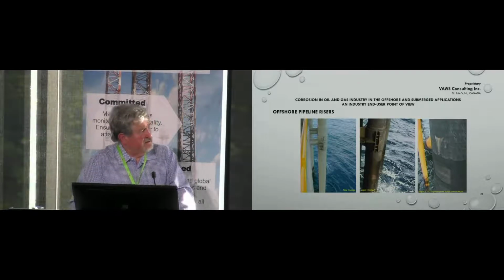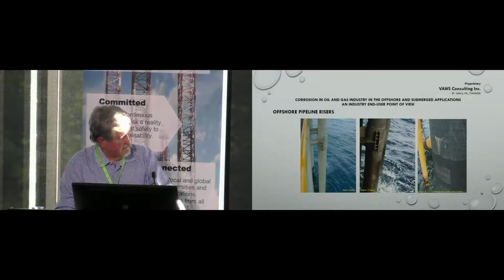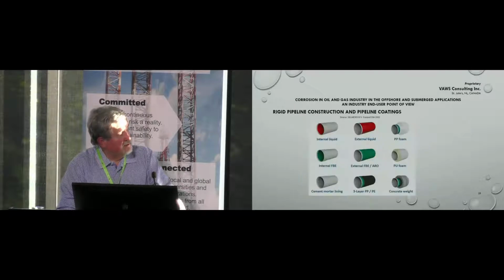Here are typical risers, the old way, the hard pipelines. A new riser after a couple of years, the paint is gone. And the very last on the right is a riser with a polychloroprene sleeve. They are very popular and they are effective if they don't get damaged. They are made in Sweden, and we had some good success with them, but if you hit it with a boat or with anything, that creates a void, and you get water behind it and they start to corrode. So again, you have to make sure that you inspect the risers.